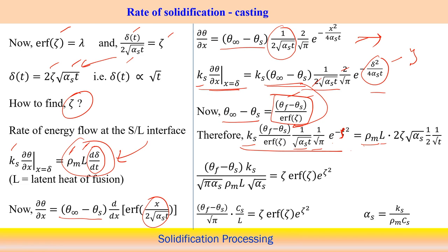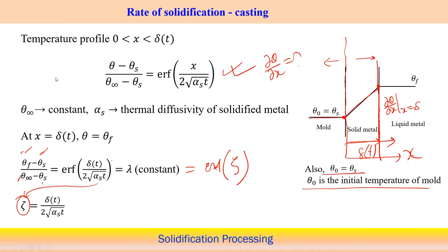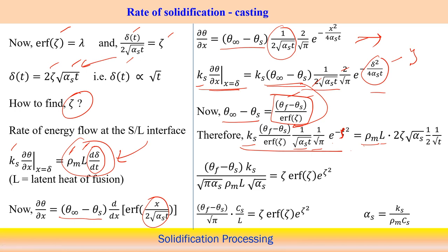So, d delta by dt we can also calculate. Here you can see that delta T we can calculate. So from here we can find d delta by dt from this expression. We can calculate d delta by dt in terms of the error function, and let us take this as a reference. So from here we can see d delta by dt, and we are getting this expression in terms of the zeta term.